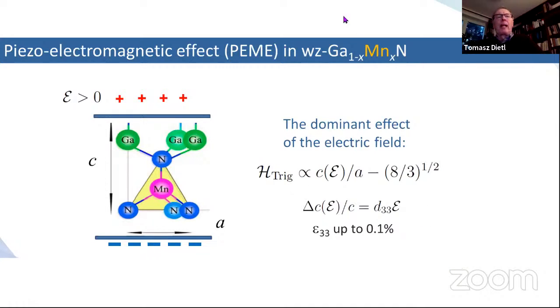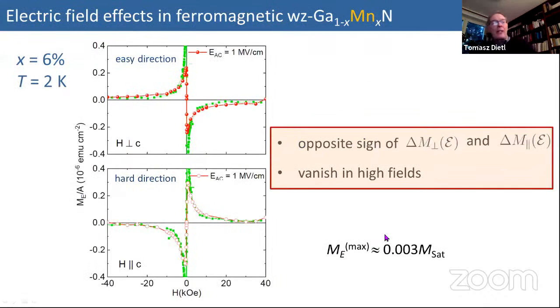So we can change the distance between this nitrogen and manganese in one direction and affect in that way the magnetic anisotropy. And this was used in the theoretical calculation, and actually we do not have adjustable parameters because we know this inverse piezoelectric coefficient, how it changes. Okay, this was ferromagnetic gallium manganese nitride.